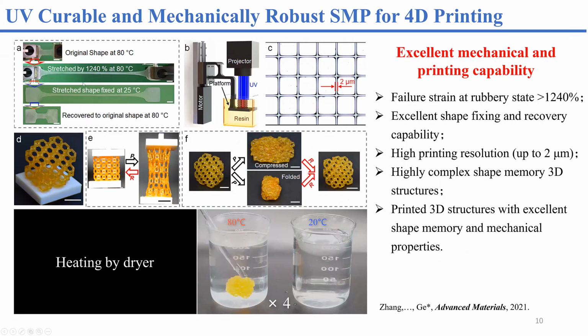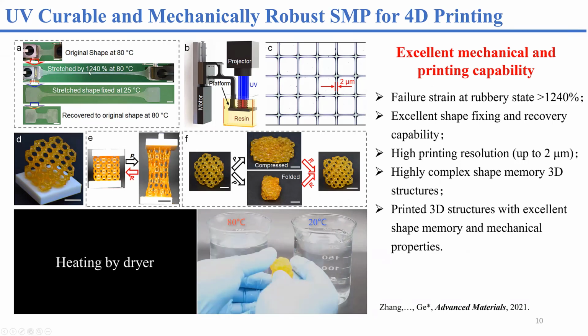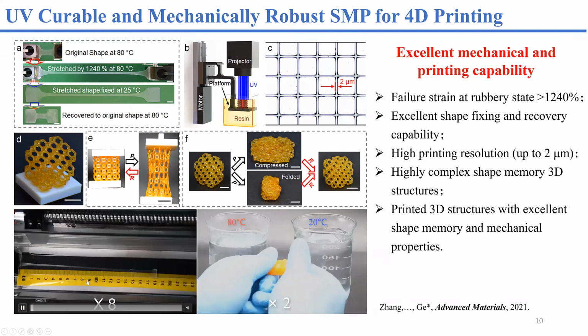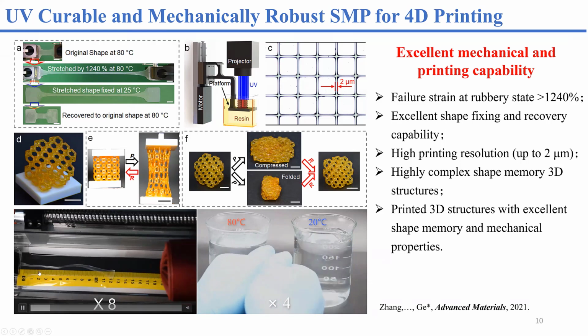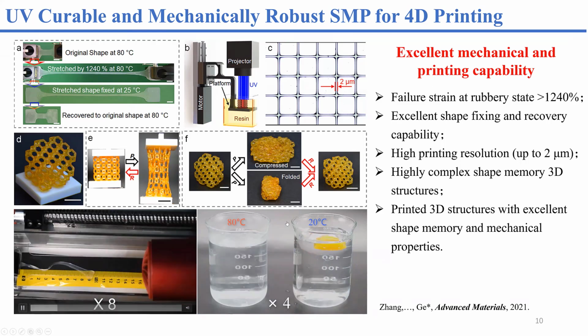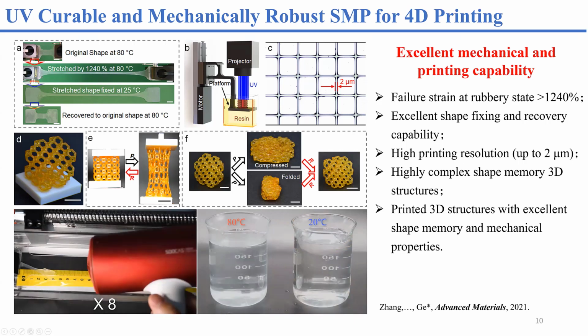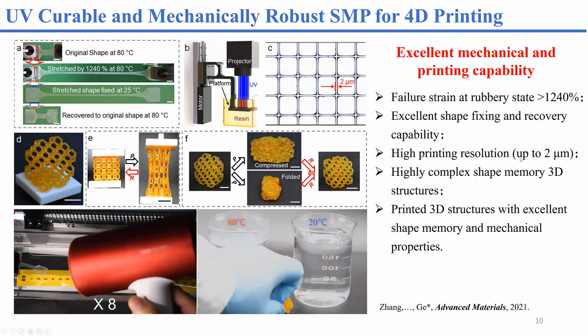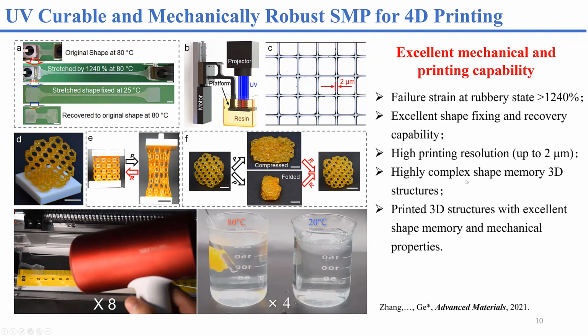For example, now we can deform the shape memory polymer with very large deformation. It can be stretched by 1,240%, and it also has good shape fixing and shape recovery ratios. When we apply heat, it quickly recovers to its original shape. And because it's compatible with DLP, and we have a very high resolution DLP printer, we can print structures with resolution up to 2 microns, and we can print very highly complex 3D structures.